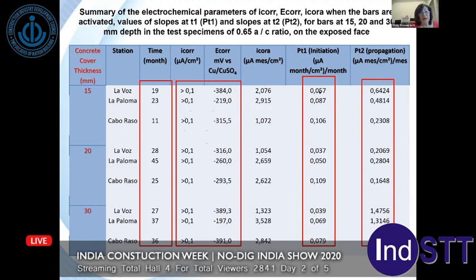It is important to remark that even so, this result verifies the adequacy of the analysis of probability and risk to estimate relative aggressiveness of a specific atmosphere. It is necessary to wait for the activation of rebar in our stations under study before determining free chloride concentration thresholds as functions of environmental variables of exposure, as well as the best model to fit the different conditions found in Iberoamerica. Ongoing work during this pandemic regime is in an advanced stage.